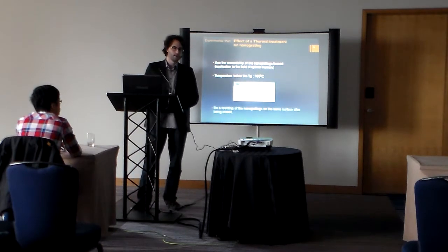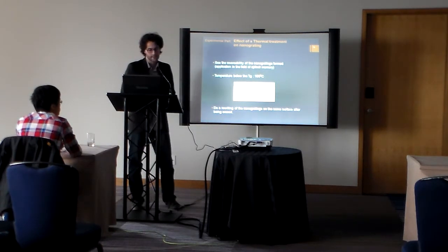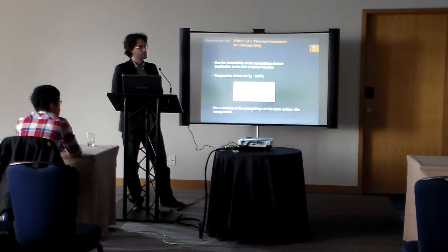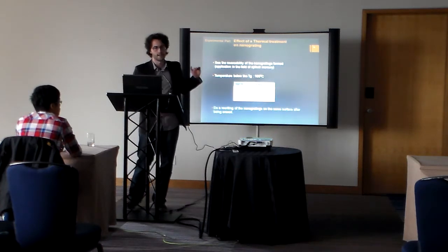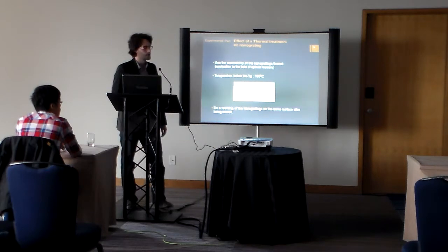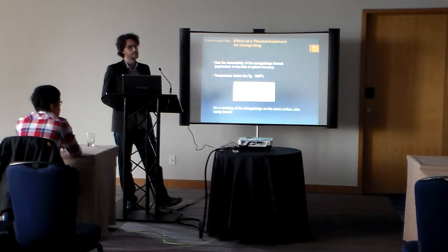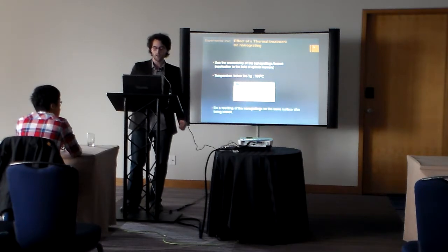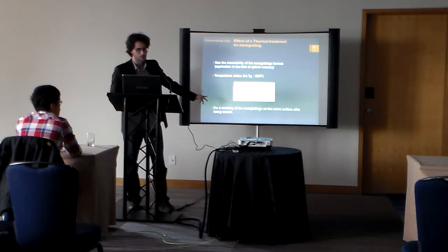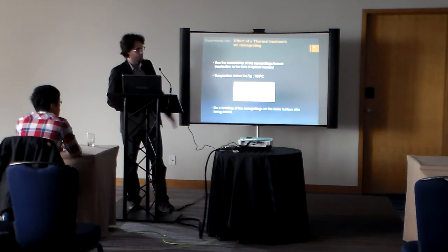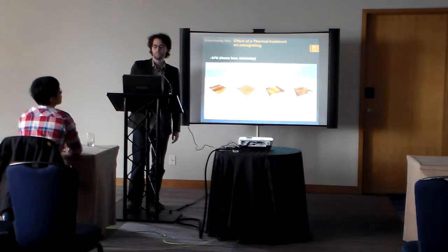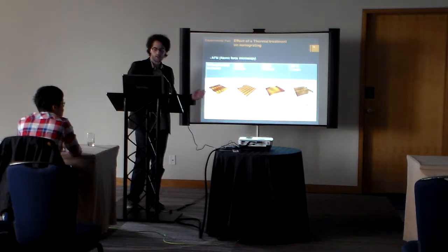We tried thermal treatment on those gratings to see if it was a reversible phenomenon. So we tried 1 hour, 6 hours, and 10 hours treatment at 180 degrees, which is a bit lower than the glass transition temperature. We also tried a 4-hour treatment with 200-degree temperature to see what would happen. And here are the results.